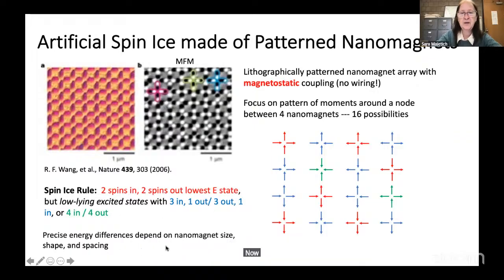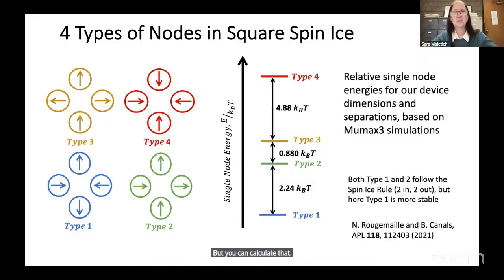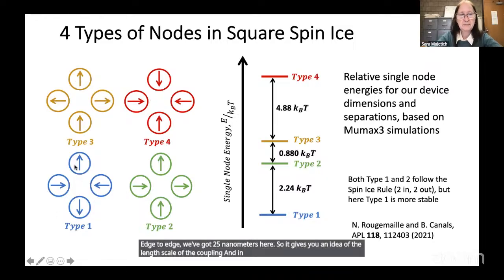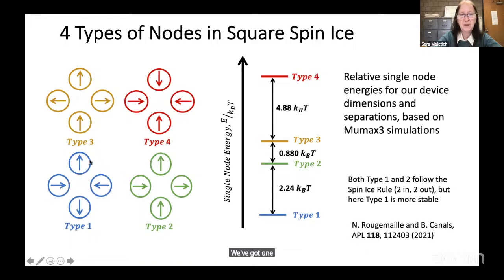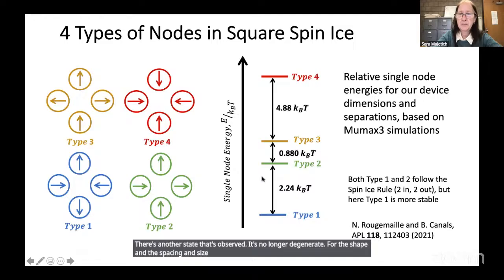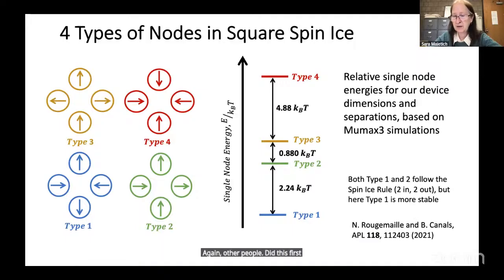Now, the relative energies depend on the size and the shape and the spacing of the nanomagnets, but you can calculate that. And that's what we did for our circular 60 nanometer dots with 90 nanometers center to center spacing. Going this way, edge to edge, we've got 25 nanometers here. So that gives you an idea of the length scale of the coupling. And in this case, we've got 1 state with 2 spins in and 2 out. That's the ground state. There's another state that's observed. It's no longer degenerate for the shape and the spacing and size. It's a little bit higher, but just a few kT. And then we have the more excited states. So you can calculate this. Again, other people did this first. We used MuMax3 for our simulations.